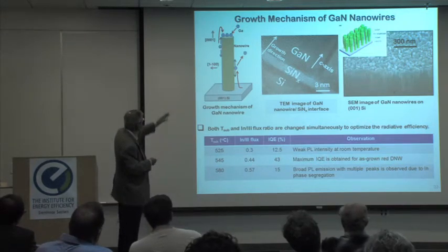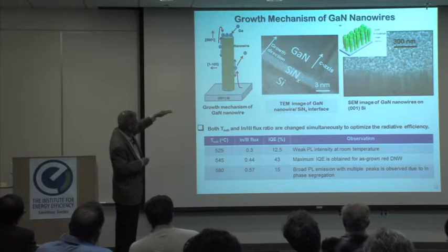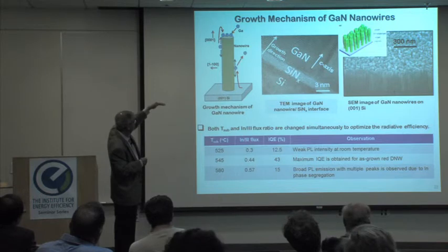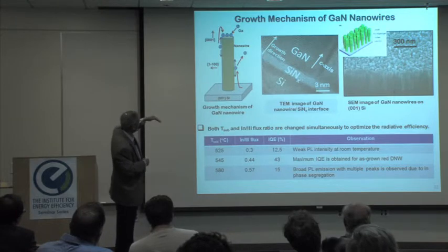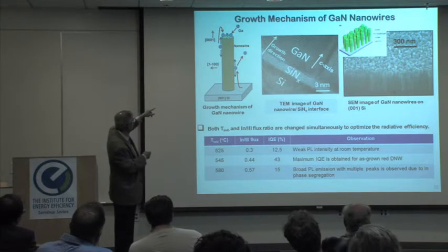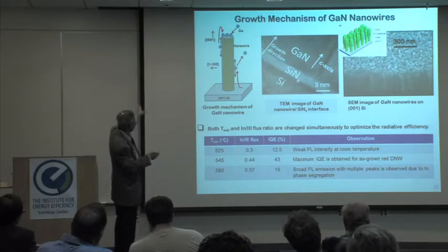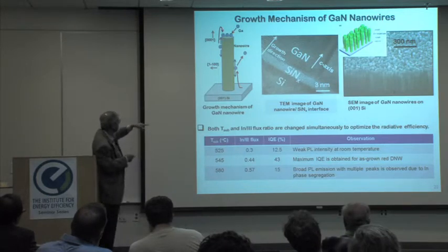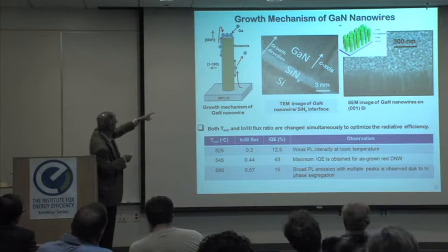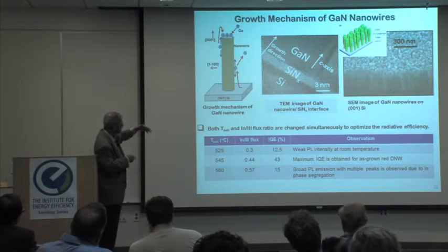So as growth proceeds, there's a large amount of incorporation of gallium, and gallium nitride proceeds parallel to that silicon nitride layer in the wurtzite form. And of course the 0001 surface is the lowest energy surface, and that's where it grows. But of course there are adatoms coming from everywhere up the walls on silicon, which has to cross the silicon gallium nitride barrier and so on. And at the same time there's a lot of desorption going on.